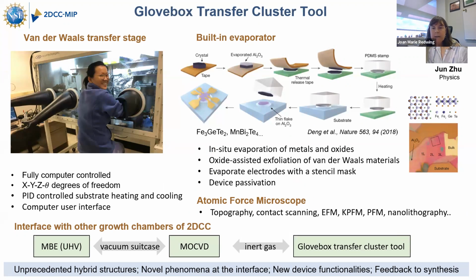And also there's an atomic force microscope that's going to be integrated into the Glovebox for scanning probe characterization and to measure the thickness of layers, and specifically when you're making stacked heterostructures. So all of this equipment will be inside a Glovebox to prevent air exposure of the layers during processing.